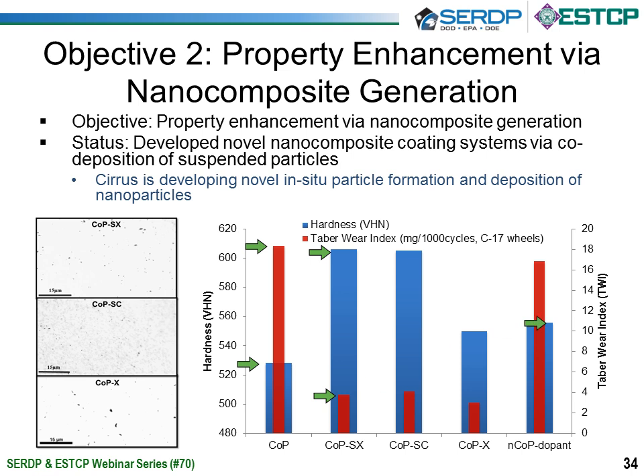The Cirrus dopant, we found that it did increase the hardness, and the Taber wear results, the abrasive wear results, did improve. However, when we looked at the cross-sections of the coating, we felt that there weren't sufficient particles co-deposited to result in a significant decrease in Taber wear. And Cirrus is currently optimizing their process and has recently resulted in new dopants that we're currently testing, and we're hopeful that they result in even better performance than we're seeing right now.